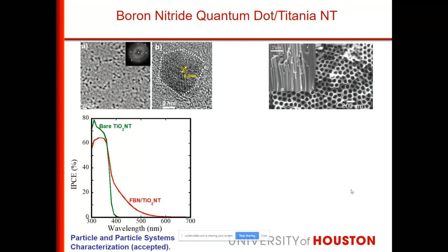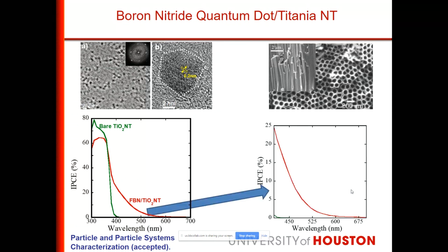And again, we studied the quantum efficiency. This time, the quantum efficiency was much higher. Earlier it was 12%. With this material, we could go to more than 550 nanometers, around the green-yellow region, and the quantum efficiency went up to around 25%. So this is a strategy we are investigating now with the new materials.